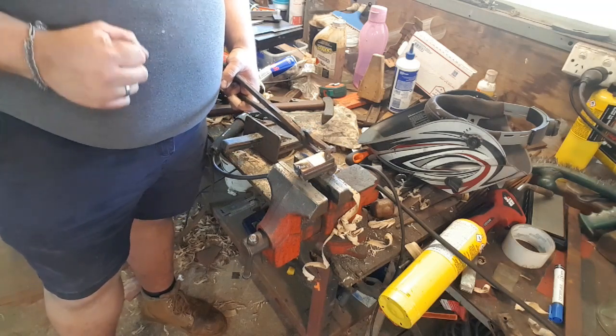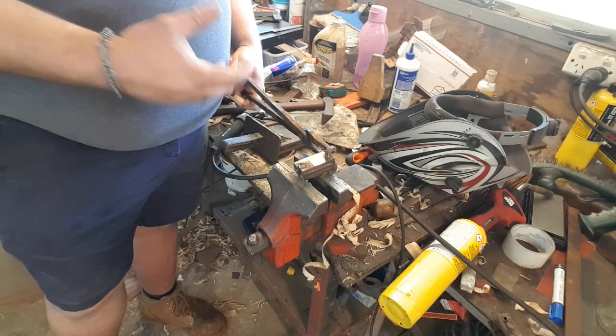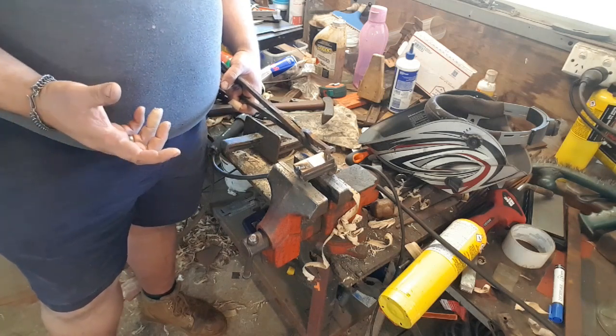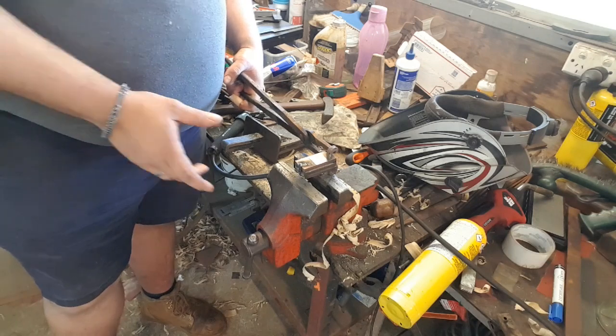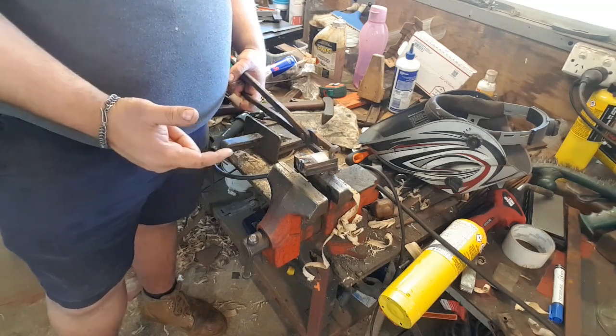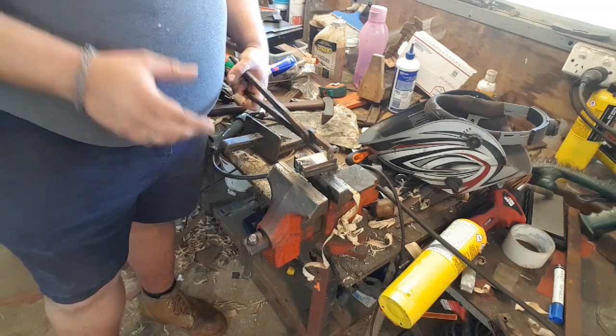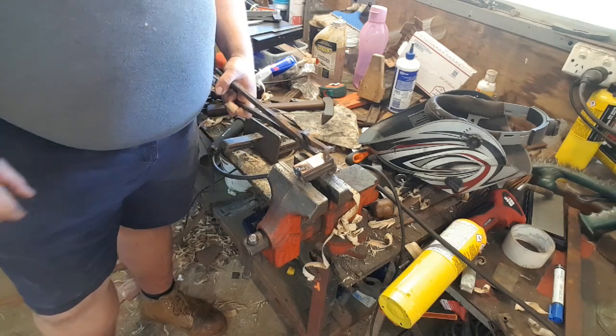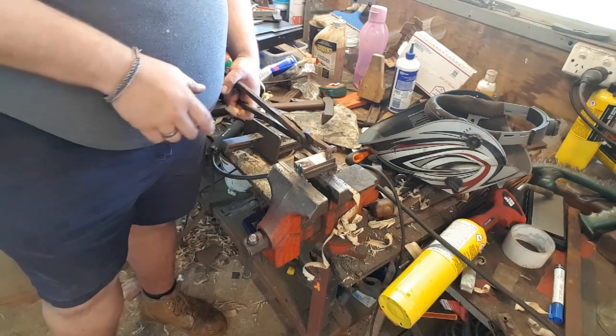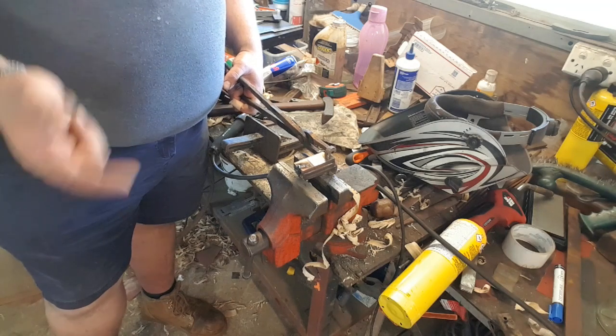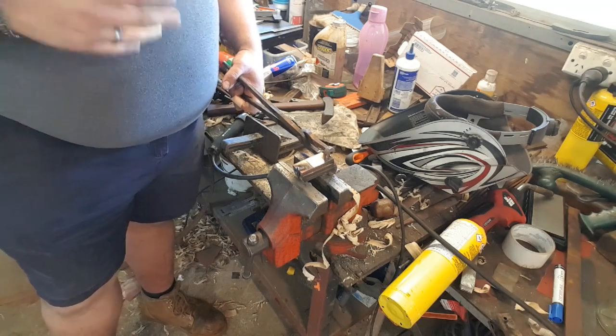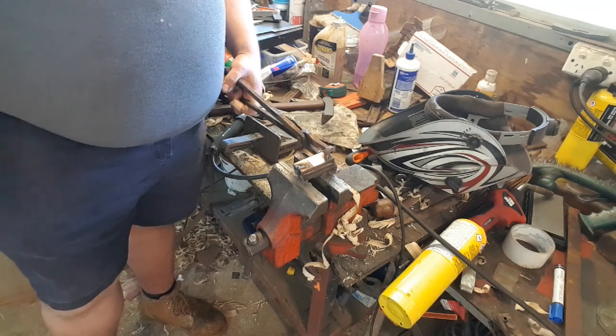Stainless steel hose clamps also work. Stainless steel won't weld in an oxygenated environment no matter how much flux you put on it. So if you use stainless steel hose clamps to clamp this all together, they won't weld. You simply knock them off at the end of the forge welding experience. If you use baling wire, it will eventually burn off during the forge welding heats. So you don't have to worry about forging that into your billet too much.